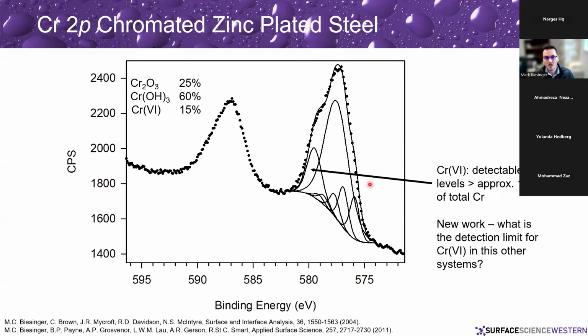If we look at something where we're trying to pull out how much chrome 6 is present, this is a chromated zinc-plated steel. And again, we're able to see, okay, we've got chromium 6 of about 15%. Because of the overlaps with all the different structures, our detection limit for chromium 6 is somewhere between maybe 5 or 10%, depending on the samples that we're looking at, within a mix of chromium 3 species.